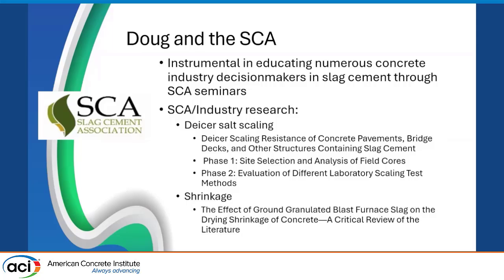The other thing we did is initiate some research with Doug. I already mentioned the shrinkage study, but there were some other de-icer salt scaling studies beyond the ones I've mentioned already. The Slag Cement Association pushed these through the Iowa State CP Tech Center, and Doug was involved in these, where he and Scott Schlorholtz went out and looked at 26 different sites which had different levels of slag, and they did an analysis of how those sites performed, and actually they did quite well. The conclusion was that if slag is placed properly, it's not going to scale generally. And then there was a follow-on study called Evaluation of Different Laboratory Scaling Test Methods, where I think the outcome was essentially a proposal that would be an alternative to ASTM C672, particularly when you're using SCMs.